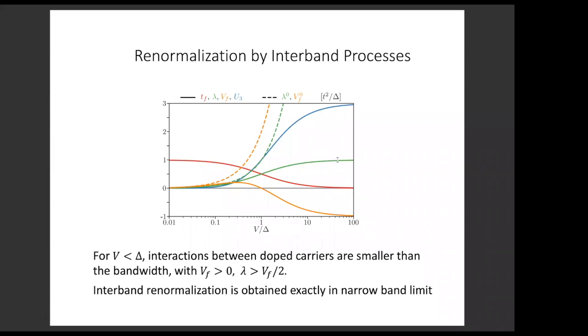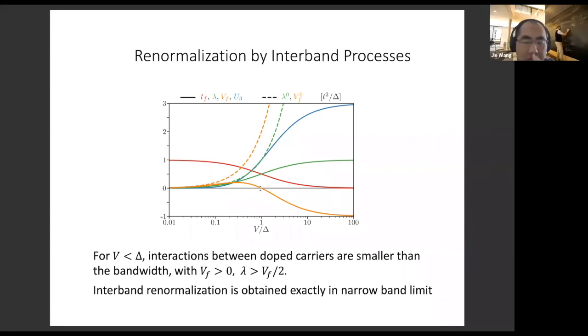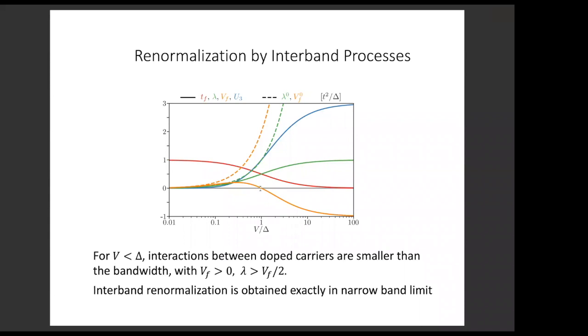And also I want to emphasize that this was in particular when V is less than delta, the induced interactions between doped charges are much smaller than the band widths. So even though the original model is strongly interacting, when V can be already on the order of the band gap, much bigger than the band width, the low energy physics of doped electrons has only a weak and intermediate interaction strength. Okay, weak and intermediate. So we've transformed the strongly interacting problem to a system of intermediate correlation for the doped electrons. So next slide.